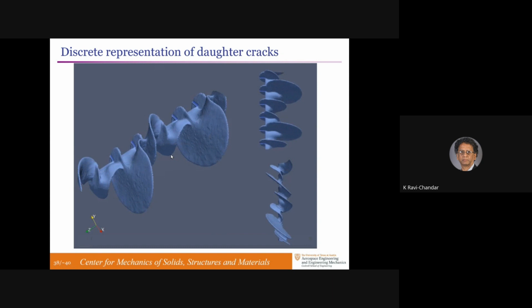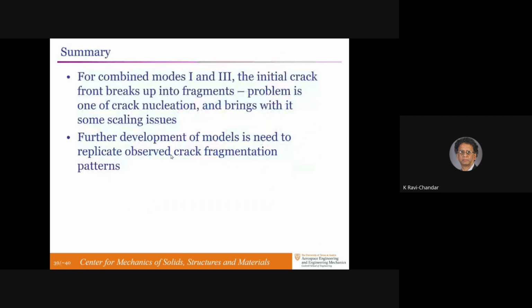We don't have enough computational capability to do this on a scale that is structural, unless the phase field method gets refined enough to be able to coarsen that length scale L0. What we've done is looked at the problem of interaction of mode 3 with mode 1 that spawns daughter cracks, or fragmentation of the original crack front, and dealt with some issues related to nucleation and growth of these. We've shown that phase field methods can reproduce some of the features, but there's an opportunity for doing rigorous simulations at larger length scales to be able to do structural problems.